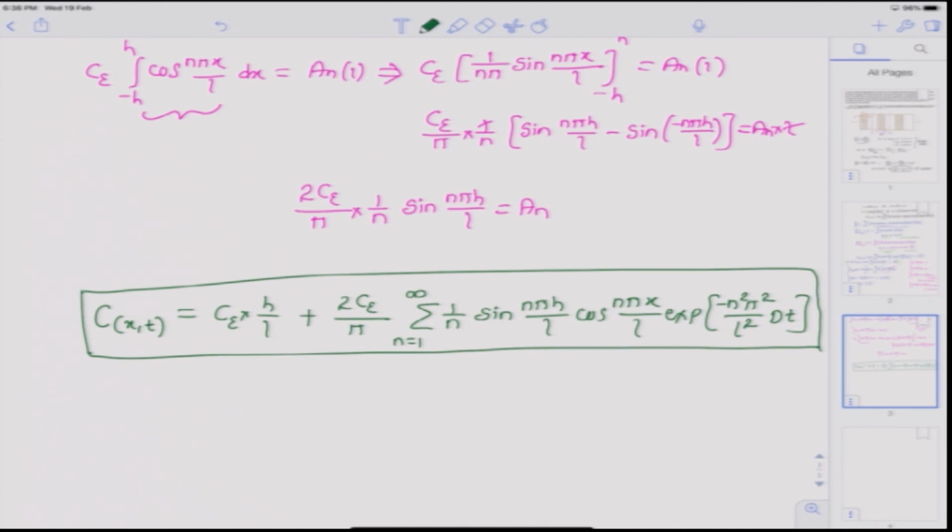Okay. So, this is how we can work with the periodic boundary conditions and solve the diffusion equation using first separation of variables and then using the series expansion. Again, we dealt here with the austenitization problem, which actually is a multi-phase problem. The concentration profile will be a little bit different because of the discontinuity at the interface at all times. As long as the interface is there between two phases, there should be a discontinuity in the concentration profile.